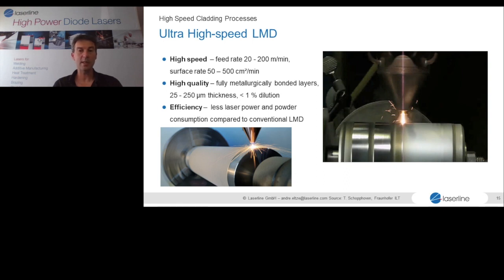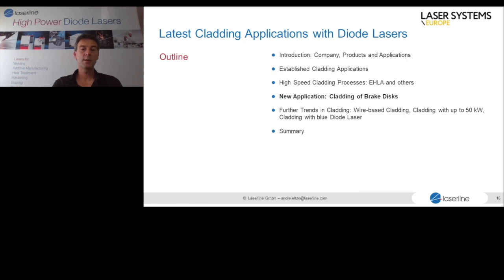Typically, as with all laser cladding processes, you will get a fully metallurgical bond, and you can have very thin layers. And because the dilution is so low, you can use thin layers where you have the full quality of the added powder. The process in the end becomes very efficient, simply because you can work with lower power, you can work with less powder because you have thin layers, so it's environmentally and also cost-wise a very efficient process. And this is the process that we use for the cladding of brake discs.